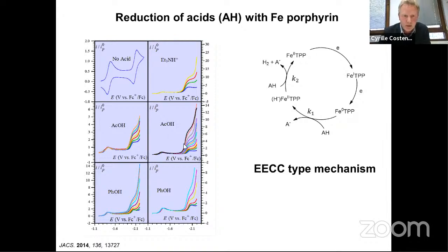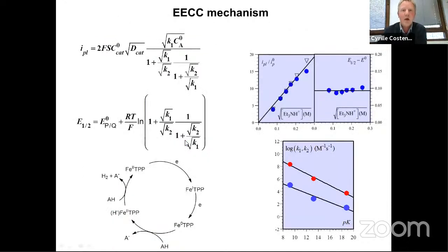Now the catalytic wave is changing while the standard potential of the catalyst is still the same. So now you are in a situation where you have two kinetic information, one from the plateau, one from the position of the wave. And in the framework of an EECC mechanism, here are the analytical expression for the plateau current and half wave potential. And as I said previously, by combination of those two information, you can extract the rate constant.